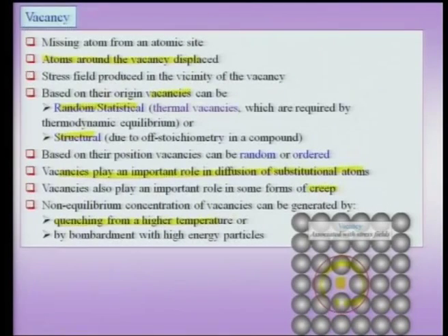But bombardment of high energy particles can also lead to an enhanced concentration of vacancies, and this is very important, especially when we are talking about materials involved with nuclear reactors, etc. So, we can have an equilibrium concentration of vacancies or a higher than equilibrium concentration of vacancies, and I have just outlined two methods by which we can produce a higher than equilibrium concentration of vacancies.